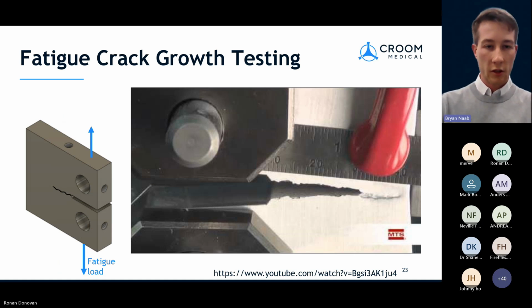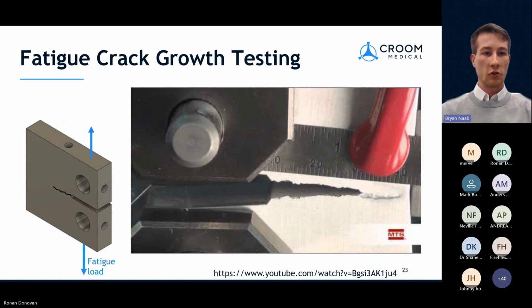So the test I mentioned previously is very much crack initiation driven, but there is, of course, fatigue crack growth to consider as well. So there's a separate test for this. So I'm showing a video from MTS here. Essentially, there's a standard specimen type which can be used to simulate fatigue crack growth, and we can measure the growth of that crack as it moves through fatigue cycles. Now, I should say this test has been sped up somewhat, but this test could take anywhere from a couple of hours to a couple of days.